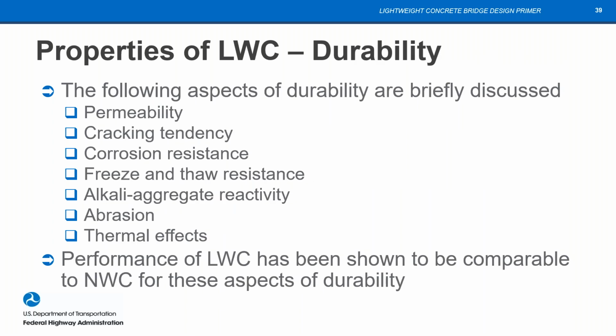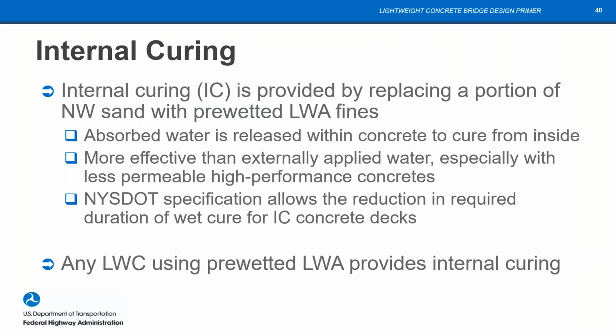The primer also discusses a number of aspects of durability. You can see them all listed here. Typically, the lightweight concrete can be shown to have comparable durability to normal weight. I won't be able to go into that in further detail. Again, there's some discussion of internal curing. I've already mentioned that. The New York State DOT has a specification now that allows a reduction even in the required duration of wet cure if you have internal curing with lightweight aggregate in the deck concrete. Also, any lightweight concrete that's using the pre-wetted lightweight aggregate will provide internal curing.